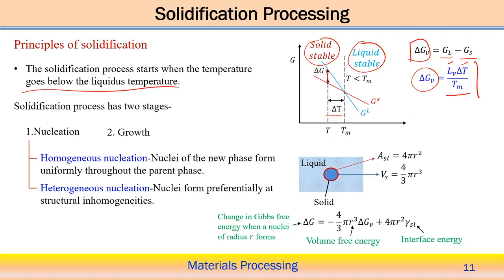And we can see mathematically what driving force is required for the homogeneous as well as the heterogeneous nucleation process. We can represent it like this. This is the liquid phase, and a solid nucleus will try to form, and once the solid nucleus forms, it creates an interface. The surface area equals 4 pi r squared, as we are assuming a spherical shape, and the volume equals 4 by 3 pi r cubed.